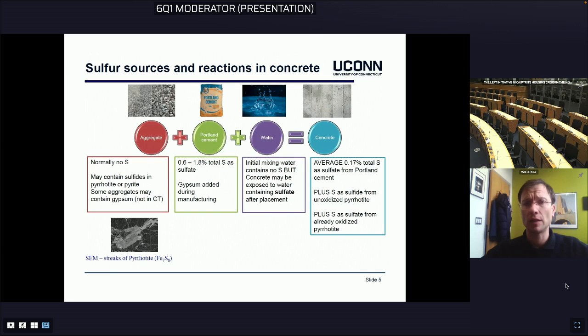Water usually does not contain any sulfur, but the concrete may be exposed to some sulfur or sulfate sources, which may then ingress into the concrete. So we might need to account for this too. When we test the concrete, we need to be aware that there might be a base level of sulfate in the concrete coming from the cement, plus there might be some sulfides from the aggregates, plus there might be some sulfur coming from oxidized pyrrhotite, which comes from the aggregate. Next slide, please.